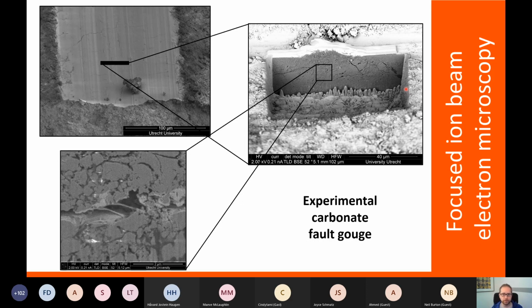Just a small side note, nowadays you cannot only have gallium ion beams as a FIB, but you can also have plasma FIBs, which allow you to ablate much larger areas on a millimeter scale. But nevertheless, once you have cut into the sample, you can actually use the power of the electron microscope to get very high resolution images. Here the field of view is 5 micrometers to try to understand what was happening below the surface. So this is conventional cross-sectioning within the focused ion beam, making the full power of manipulation using the gallium ion source in the imaging of the electron microscope.